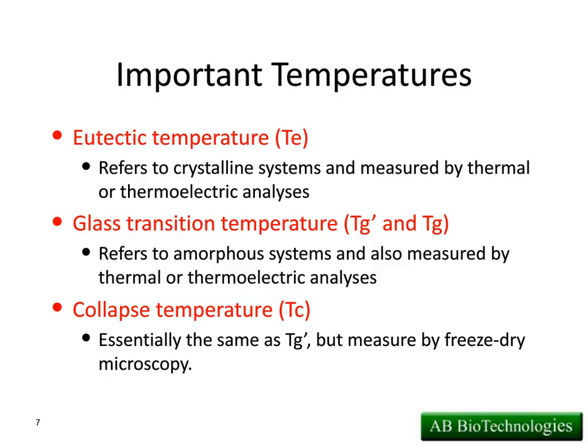So again, it's very important to be below these critical temperatures. The collapse temperature down at the bottom, this is very close to what we would call the TG prime, the glass transition temperature, but it's a little bit different. The first two points here, we would measure with differential scanning calorimetry. The collapse, we use a freeze-dry microscope to do that. And we'll talk as we go along about what each of those pieces of equipment offer to the complete thermal package, if you will, for our sample.